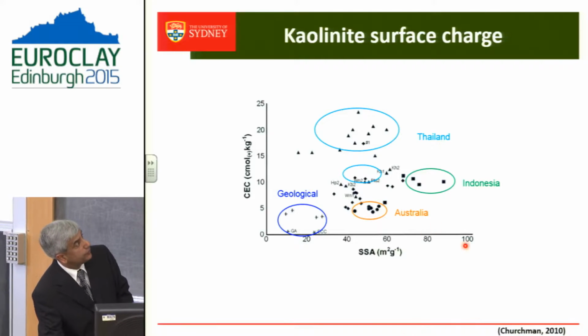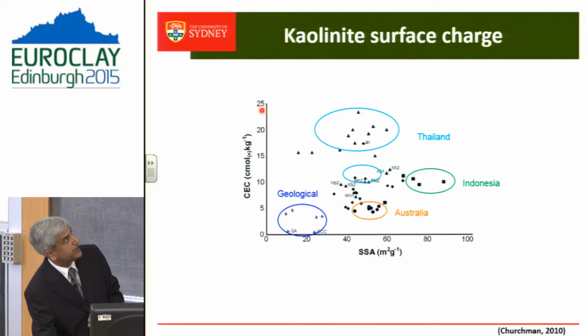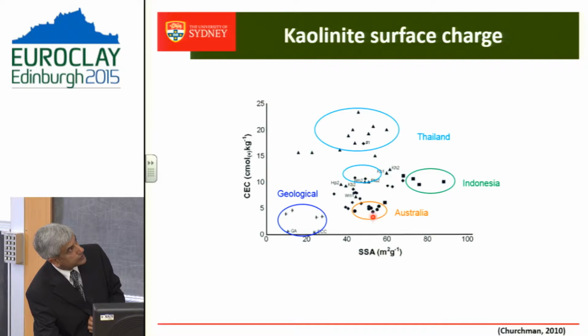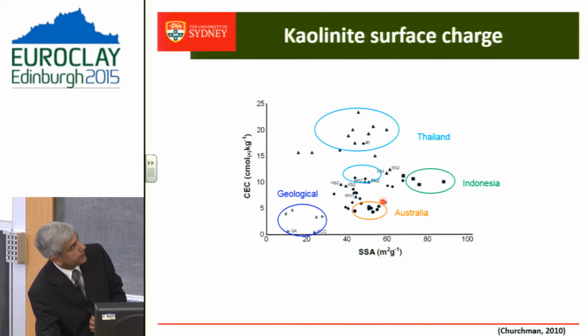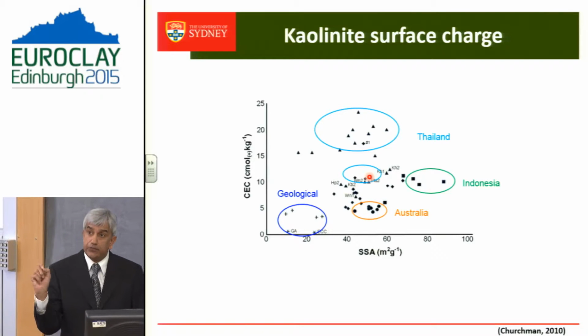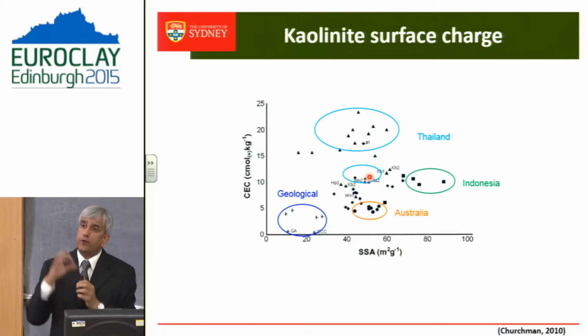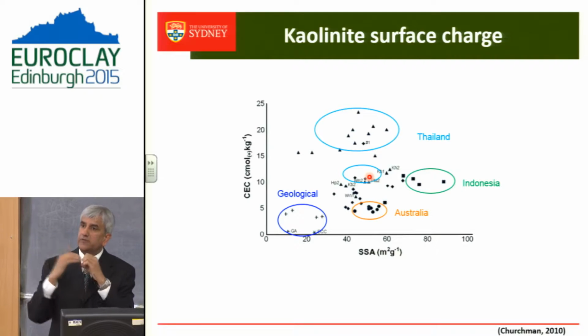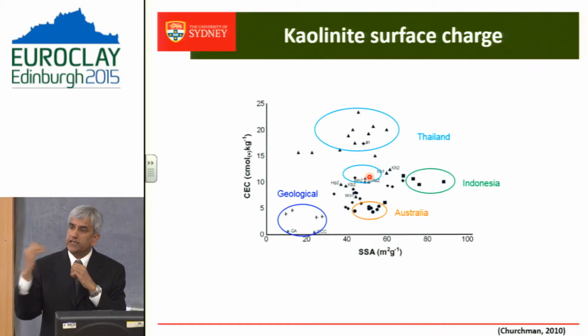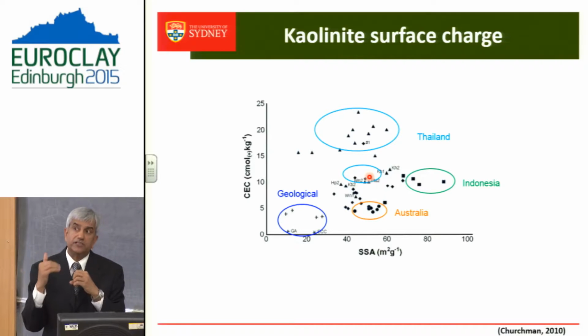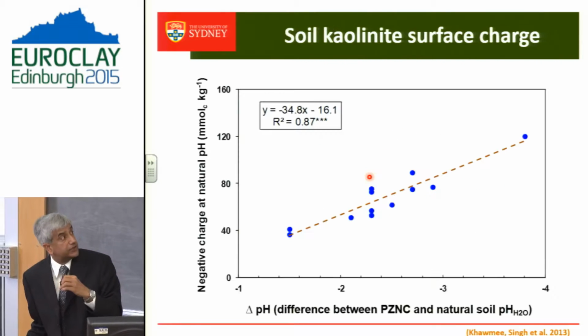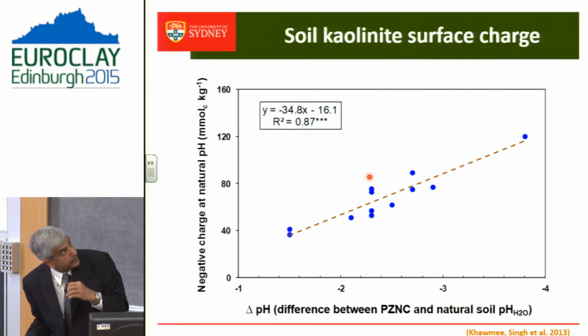Jock Churchman has produced this relationship between surface area and exchange capacity. That's where you can see most of the kaolinites have got cation exchange capacity between 5 to 10 centimoles per kilogram compared to the geological sample. So they are much more reactive. Why are they reactive? Probably a combination of much smaller size, and those surface functional groups contribute a lot more exchange capacity. Also there is substitution of iron in the structure, and I will probably skip this one.